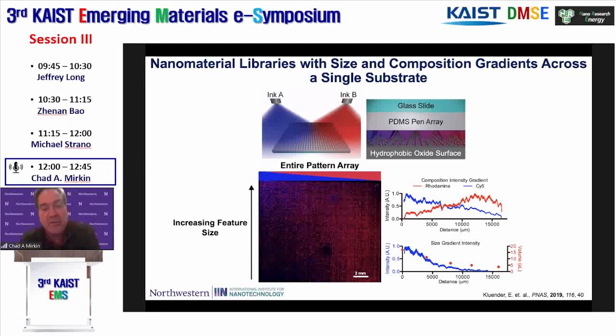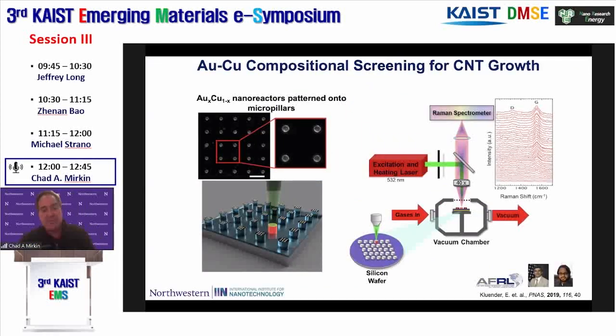The first Megalibraries we made were made in the following way. We basically take polymeric gradients that have different metal ions in them and spray on the array of pens materials, build a gradient of materials. Flip that around. Every time you come down with a commercial tool, 160,000 pens deliver 160,000 slightly different features. Do that over and over and over again. Use time to control feature volume, and you soon can go from hundreds of thousands to millions and ultimately billions of distinct particles. We typically make about 150 to 225 million particles per library, per megalibrary. Okay, that's how you make them.